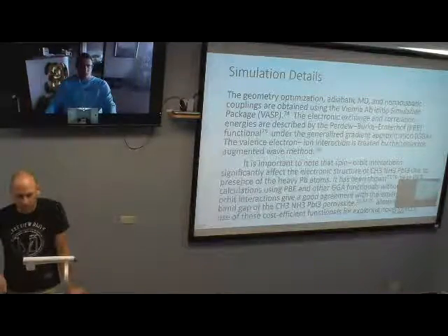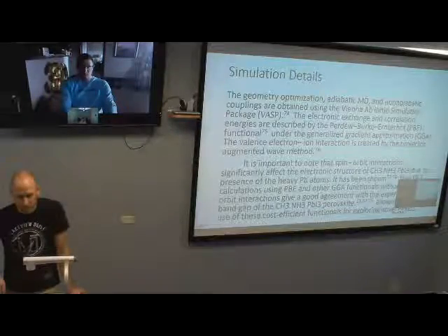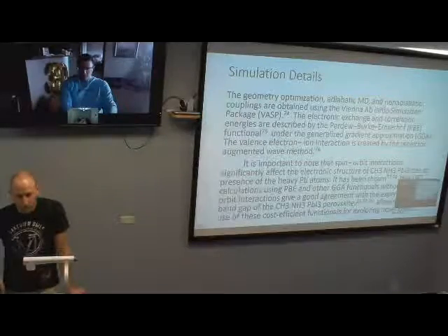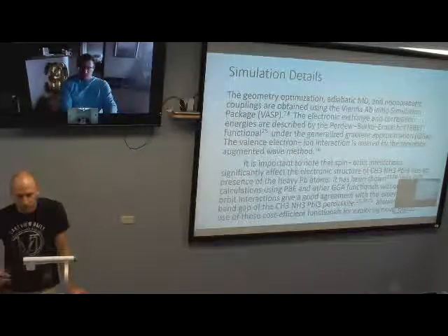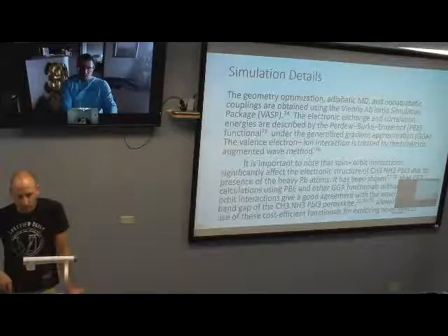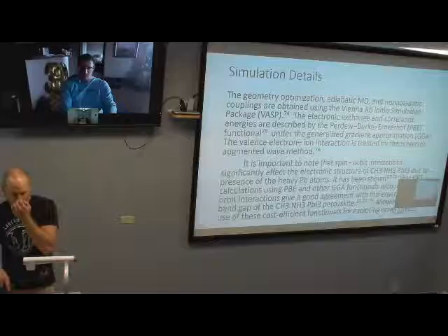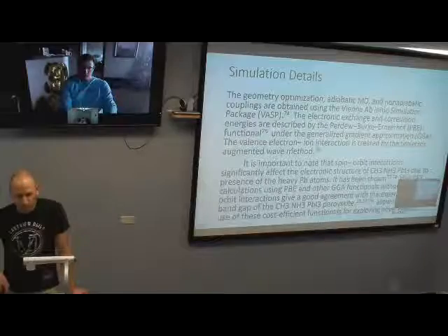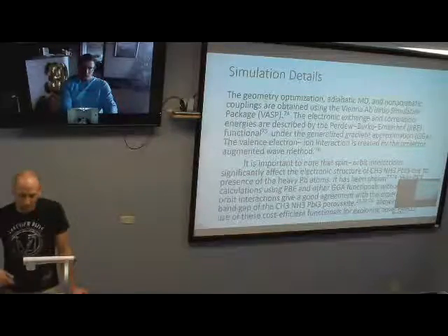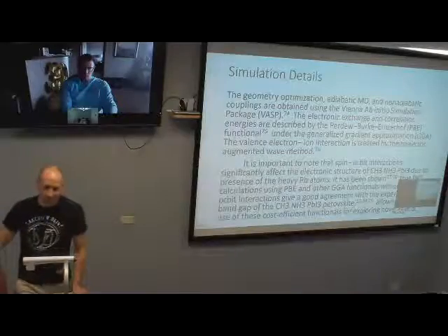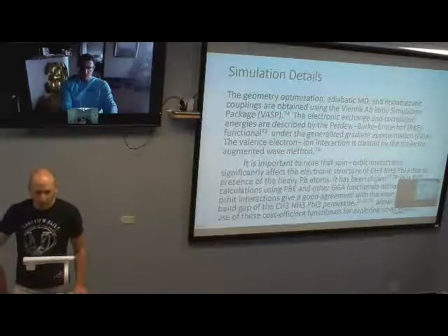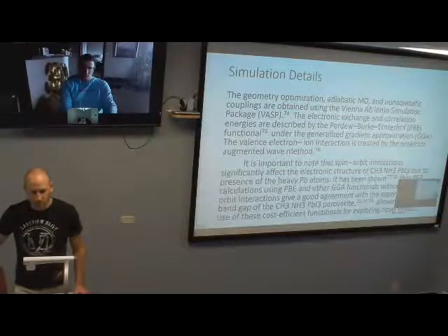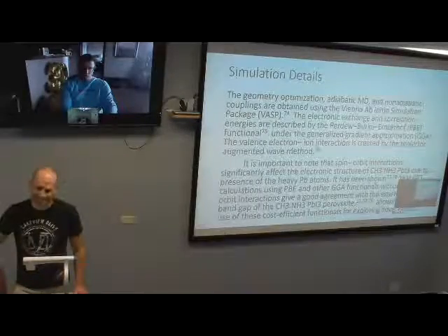To be accurate, you need to include the excitonic effects, and probably also improve your functional for the exchange part with hybrid functionals or GW correction, which is pretty much the same. But then you also need to include the spin orbit. And if you do everything accurately, you will get energy gaps which can actually be reproduced by PBE. But PBE reproduces it for the wrong reason, just because it makes the gap smaller. In real systems, it's smaller because of the contribution of other terms which you have to include when you improve your functional. Okay. Yeah.